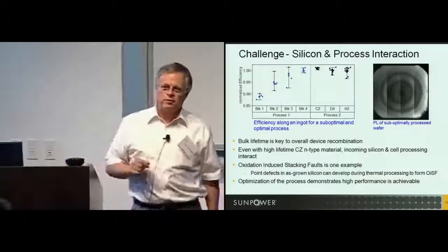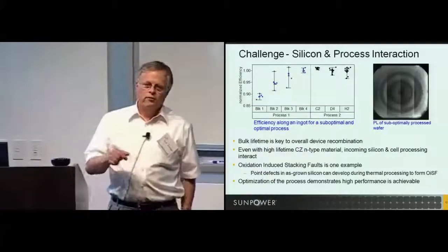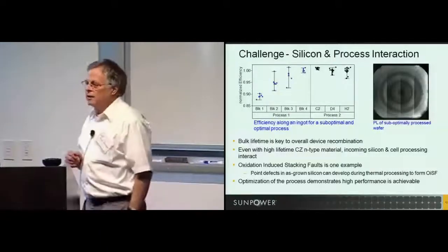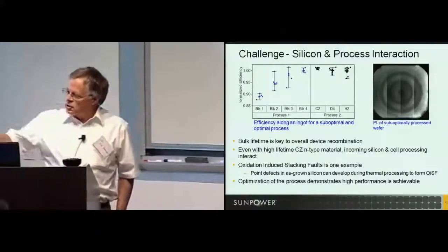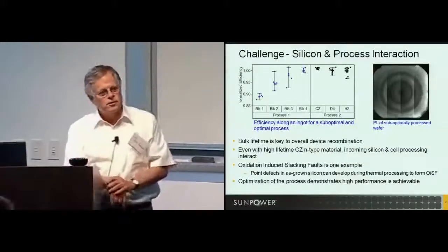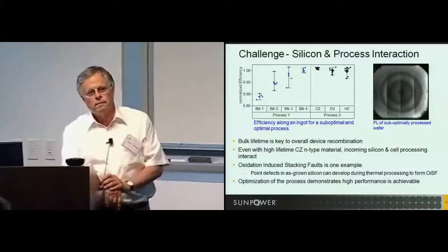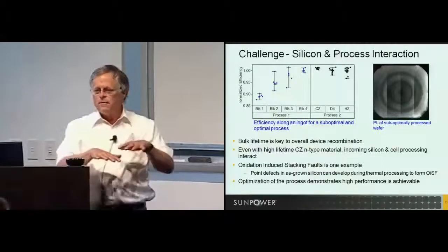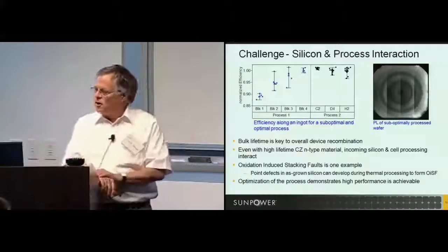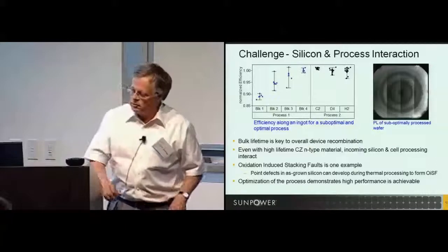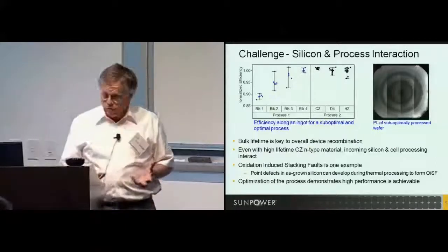You just shoot a picture of a panel running current through it, running it backwards as an LED, and you'll see it very dramatically. This is shown here just because there's some very interesting physics that goes on inside this growth of the material that are called striations. The lifetime, the defect density in the cell actually has this radial symmetry and waves that go out due to the material science of the growth process.